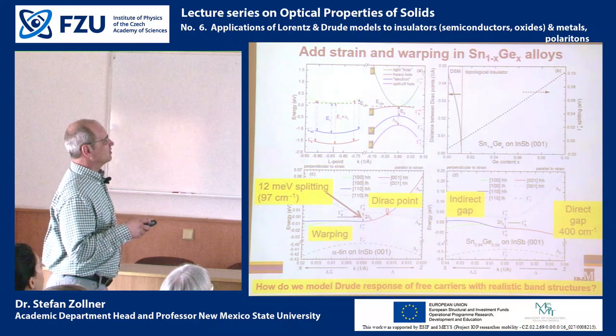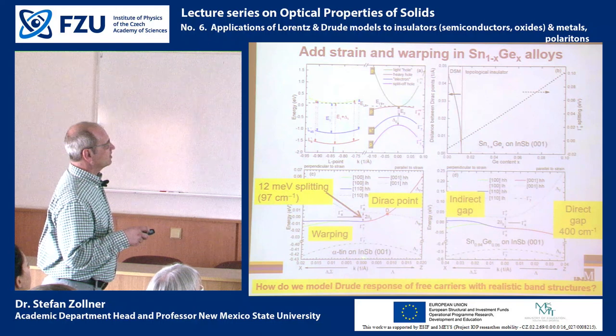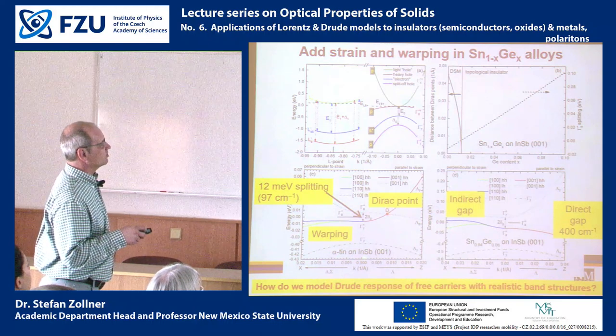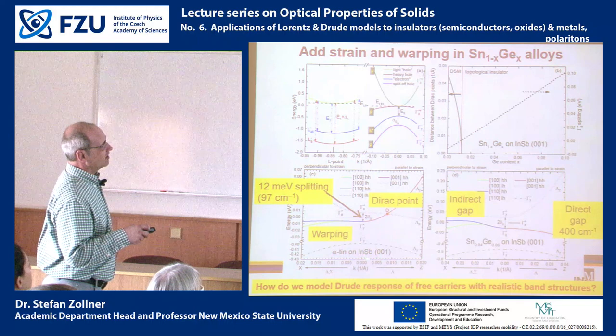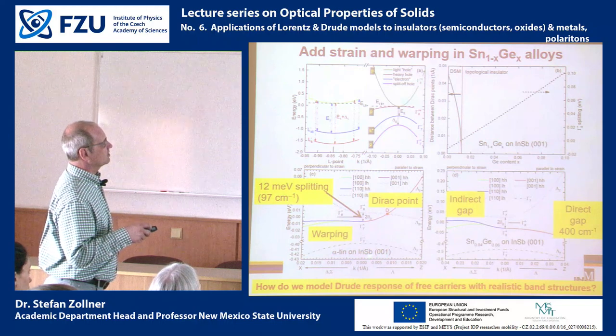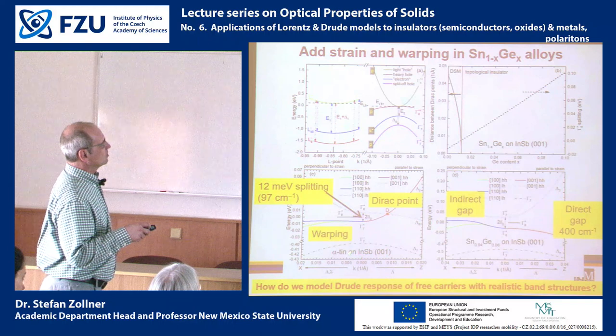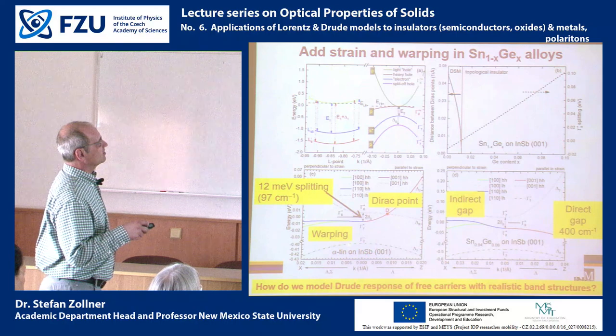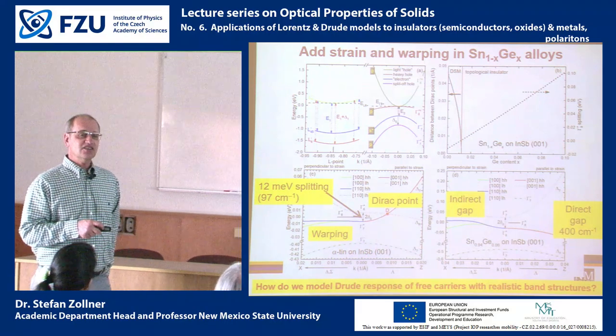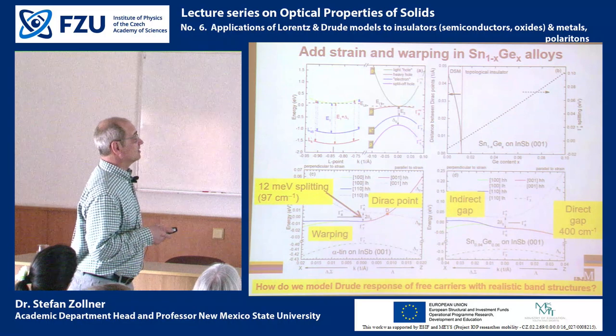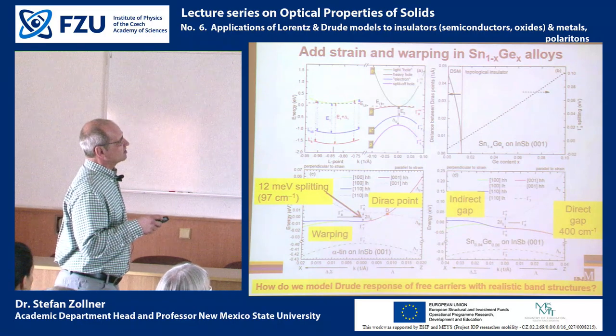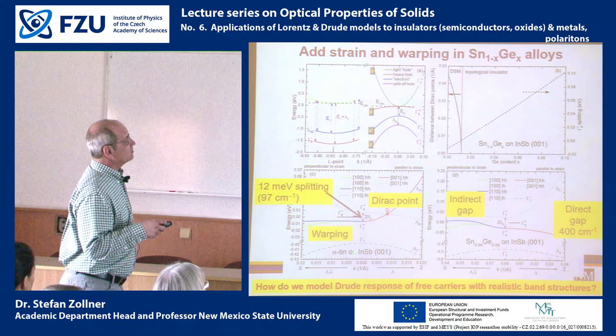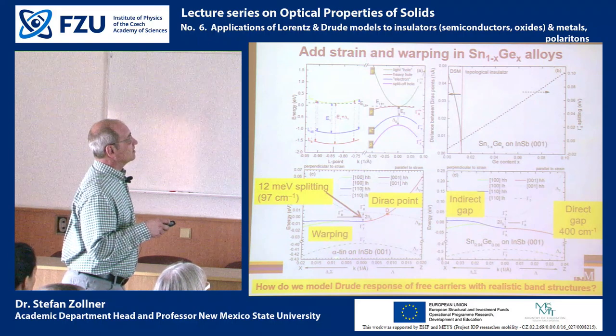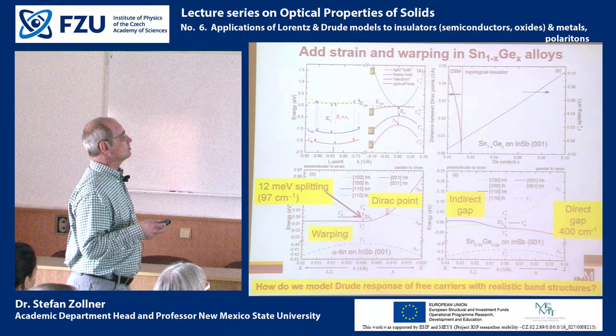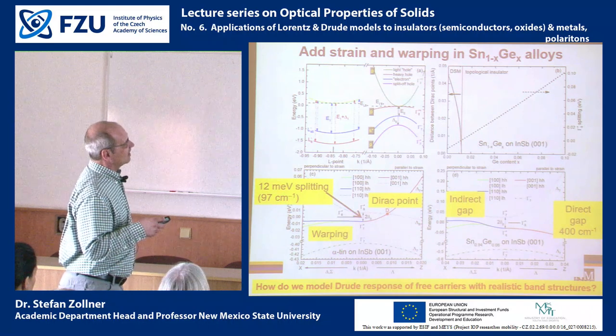So, for example, a common substrate on which to grow alpha tin epitaxially is indium antimonide, and cadmium telluride is another substrate that has been used. So you grow alpha tin on indium antimonide, but because the lattice constant of alpha tin is not exactly equal to that of indium antimonide, the alpha tin is under strain, and therefore we need to include the strain in our calculations.